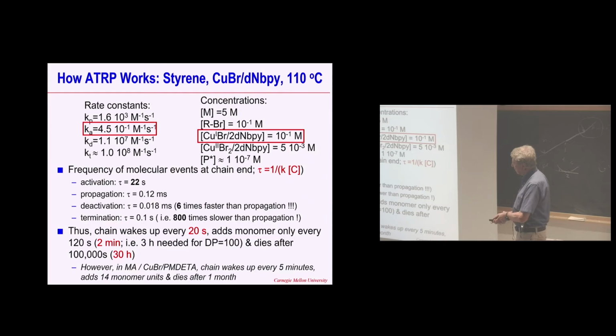So if I take another system, for example methyl acrylate and another ligand, copper PMDETA, the chain wakes up every 5 minutes, adds 14 monomer units, but dies after 1 month. So it would be 15, 30, 45, 60 on average. Now, in the case of styrene, the chain wakes up every 20 seconds, but adds monomer 6 times slower, so every 2 minutes, and to get DP 100, I would need 200 minutes, 3 hours, and it dies after 30 hours. These are just examples to give you a little bit of a feeling for how these reactions can occur.